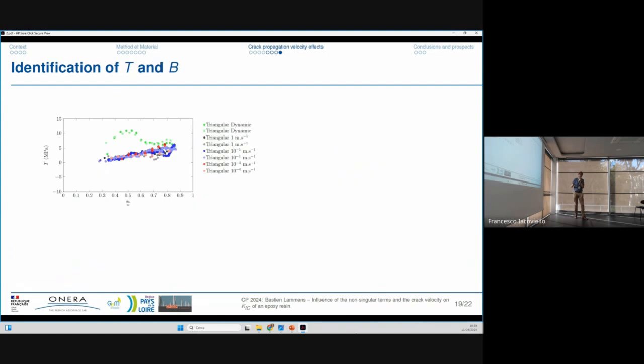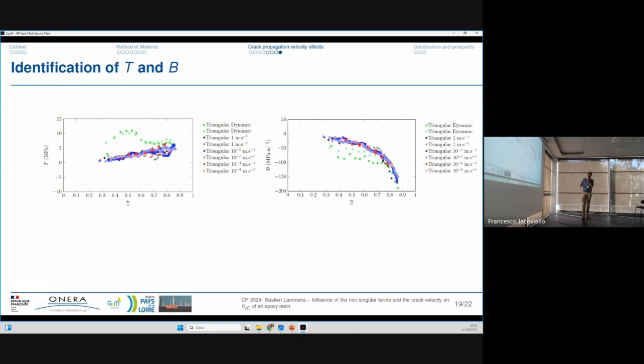And now, if you look at the non-singular terms, we can see the evolution of the T-stress with the normalized crack propagation, and we can see two trends. The first one is for the sharp tip, and the second one is for the circular notch. For the B stress, we have a decrease of the B stress during the crack propagation, and the difference between the results can be explained by the type of the notch, sharp or circular notch.